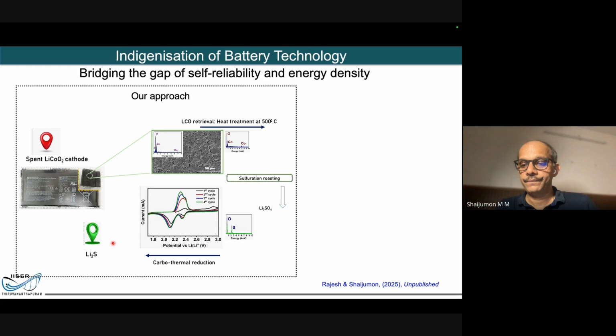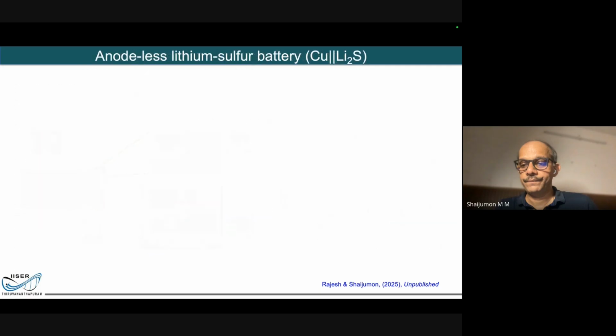So instead of getting the lithium cobalt oxide restructured and using it for a lithium-ion battery, what we have done is very cleverly, using very simple reactions, from a spent lithium-ion battery, from a spent cathode, we were able to get this lithium sulfide. And this Li2S is a cathode for a lithium sulfur battery. So that's an exciting approach. Actually filing a patent for that. It's a very new work. I'm not supposed to talk about much details about it, but I thought I'll just mention this.